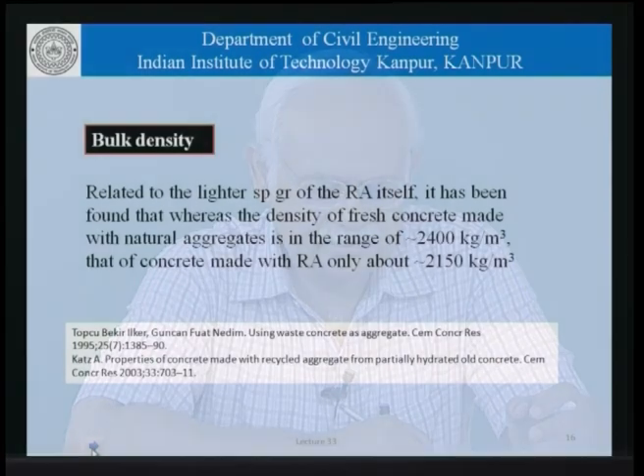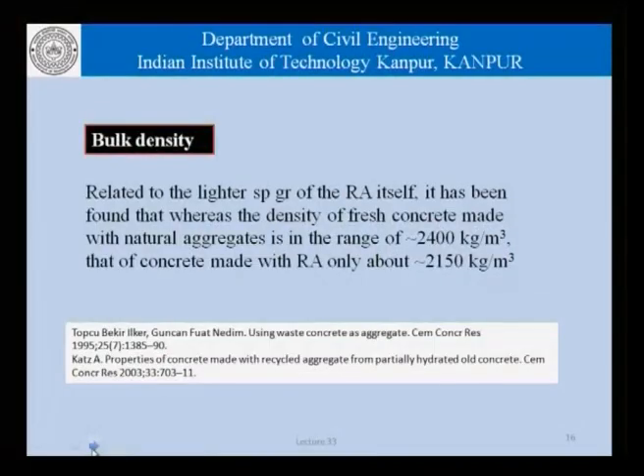and as far as bulk density is concerned, it is related to the lighter specific gravity of the recycled aggregate itself. And it has been found that whereas the density of fresh concrete made with natural aggregates is in the range of about 2400 kgs per cubic meter, that of concrete made with recycled aggregates is only about 2100 or 2150 and so on.